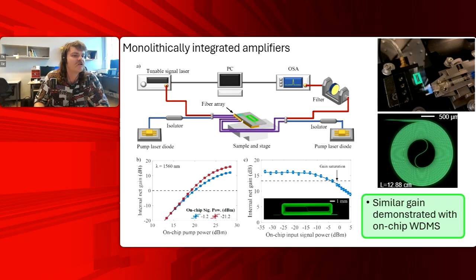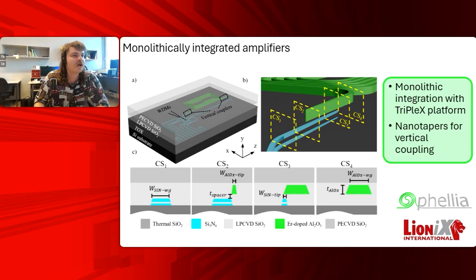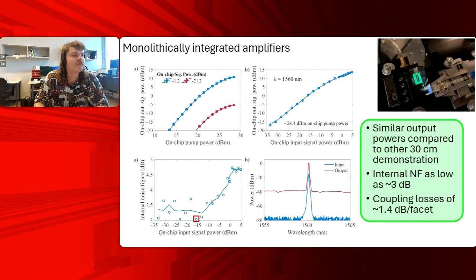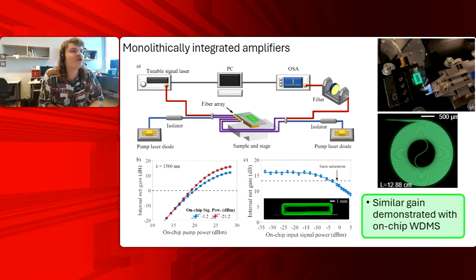You can see I have internal gain listed here, but the coupling losses are 1.4 dB per facet. So just at that same kind of gain value has been achieved on top of silicon nitride waveguides, which is very exciting. And you can see here proof with that green spiral, the green diminishing as it goes down to the silicon nitride, with that characteristic glow not being present, of course, in the material that's not being amplified.